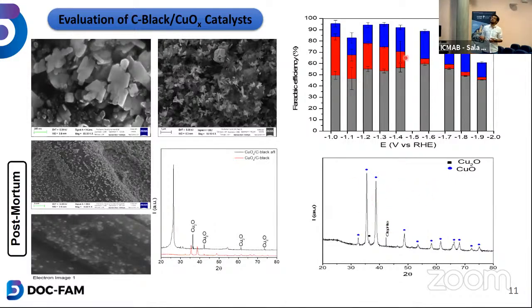When I tested in the flow cell, initially at -1.4 or something, I have a decent amount of CO and ethylene. But when I'm sweeping more negative, like at -1.7 or something, I could see very high amounts of ethylene, almost 35%. There are stages where I reached almost 40% of ethylene, which is quite a good number, as we expected.